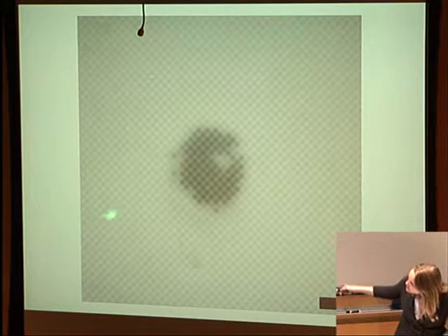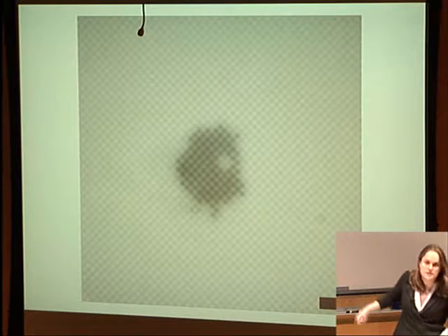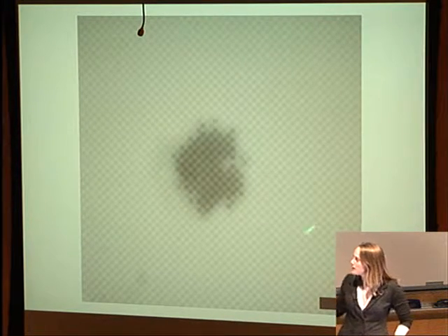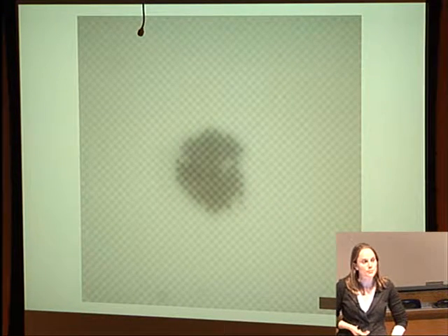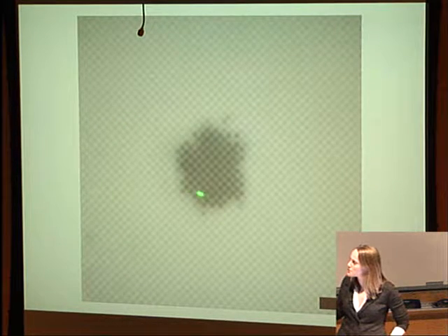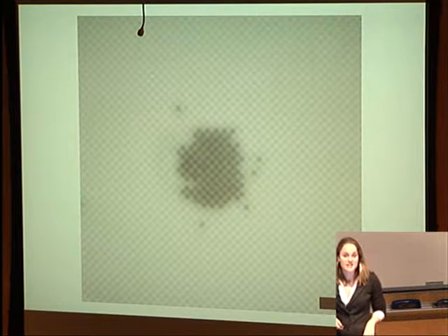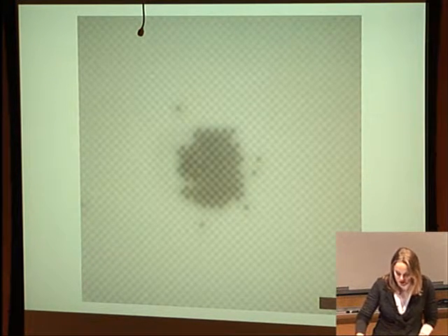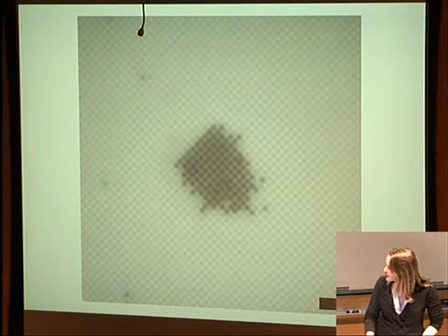So in this experiment, we've built this 2D crystal. These are polystyrene particles with 500 nanometer diameter. And the lattice constant here is about 820 nanometers. The light we're using is 1.5 microns. So this is all sub-wavelength. And the particles are a little bit smaller than the lattice constant. And not only can you build these up, but it's reversible. So in the next video, we have an assembled cluster, and we simply turn the light off.